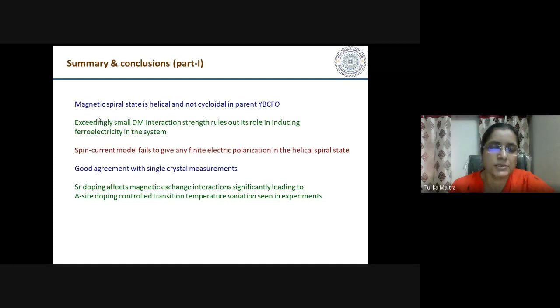The magnetic spiral state is helical and not cycloidal in the parent compound, and the Dzyaloshinskii-Moriya interaction is exceedingly small. This rules out its role in inducing ferroelectricity in the system. The spin current model also fails if there is a helical spiral state, and our observations are in good agreement with single crystal measurement. And strontium doping affects the magnetic exchange interaction significantly, leading to A-site doping controlled transition temperature variations seen in experiment.